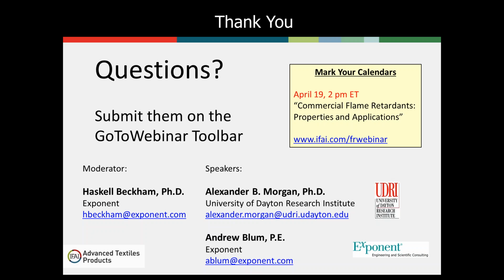One thing I like to do, if I'm running the cone calorimeter or one of these vertical flame spread tests that I showed videos of before, is to always have a baseline material around. With the cone calorimeter, for instance, they recommend, and we've found great consistent results with, burning a piece of PMMA every so often. You should get the same general range of results as far as heat release rate, when the peak comes, the time to ignition, your smoke production, all of that. If you're keeping your equipment up to speed with its calibrations and you're doing some baseline tests as well, you should be able to spot any issues that come up with, hey, why is this result not repeatable? Why are we getting bad data?